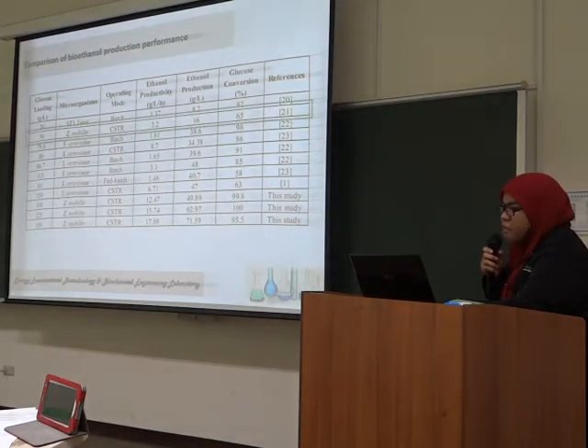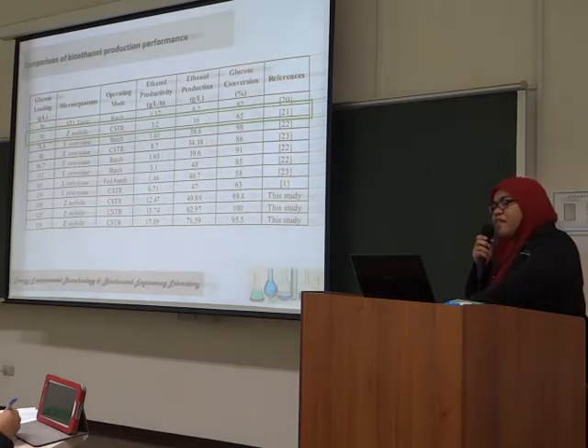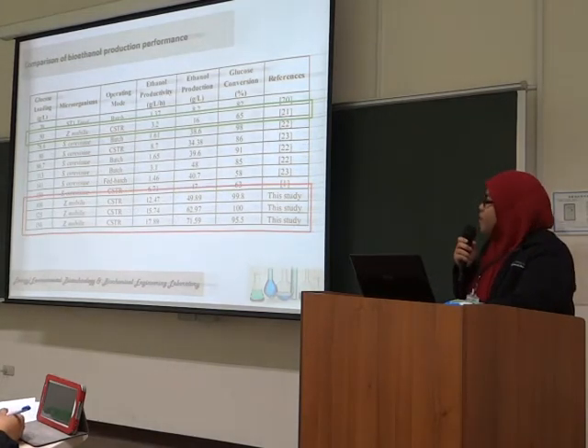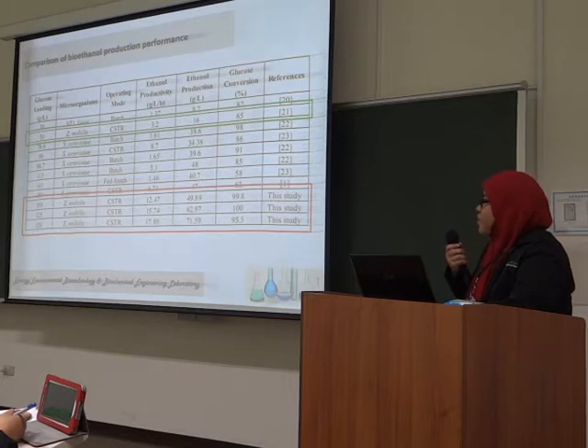And in here, I just want to compare my study with the other literature study. And this is my previous study. I also used this strain with CSTR or batch mode, but I just used glucose loading 50 gram per liter. But the ethanol productivity is still very low, only 3.2 gram per liter per hour, with glucose conversion only 65%. But right now, I tried to employ 100 gram per liter, 125 gram per liter, and 150 gram per liter. And in here I can find better values of both ethanol productivity and ethanol production. And the most important thing is glucose conversion is almost complete, 100%.